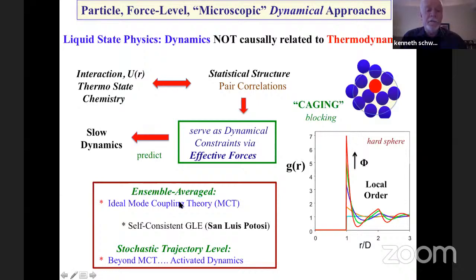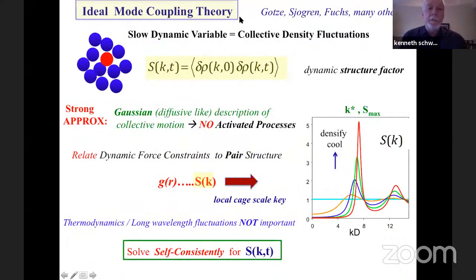So let me discuss the first approach very briefly, which is a seminal approach, the ideal mode coupling theory. The core idea is that the key slow dynamical variable is the collective density fluctuations. They are directly measurable in the dynamic structure factor, S(k,t), which is the autocorrelation function of the density fluctuation of wave vector k at time equals 0 with the density fluctuation at wave vector k at a later time. And this is measurable in many experiments.